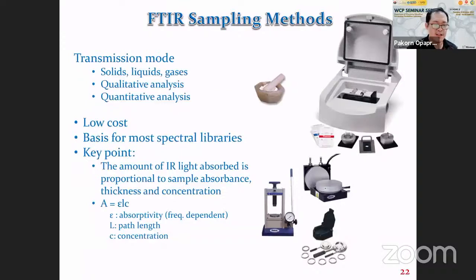So now, for transmission mode, we can measure samples in solid, liquid, or gas mode. We can apply this in qualitative or quantitative mode, by using different types of accessories, and also by combining or diluting our sample with a compound that does not absorb infrared light. The most common one is potassium bromide, or KBr. This compound will not absorb infrared light, so we can use it to dilute our sample in order to get a high quality spectrum, especially if we want to do quantitative analysis.